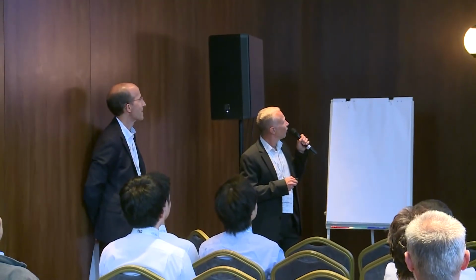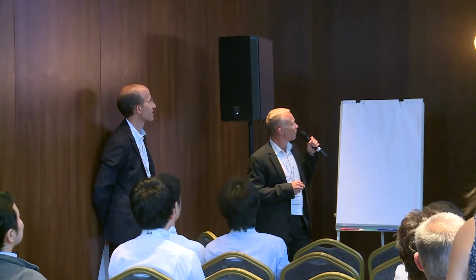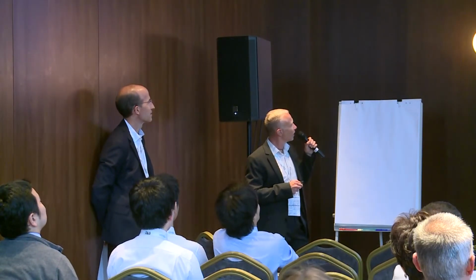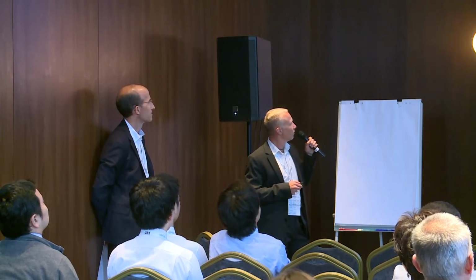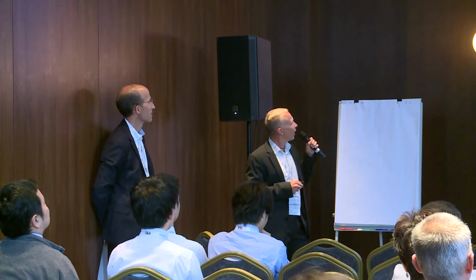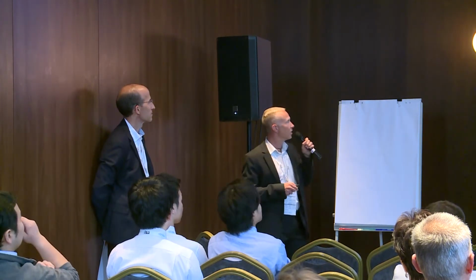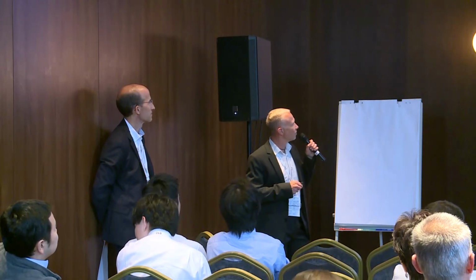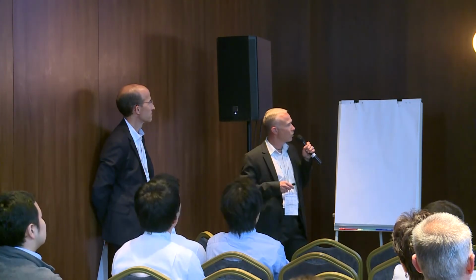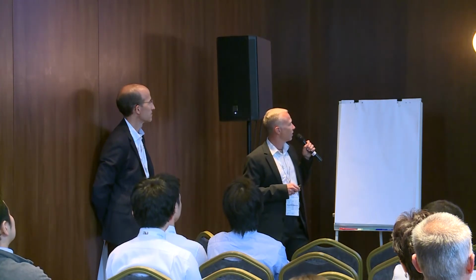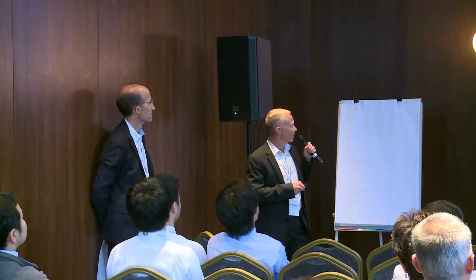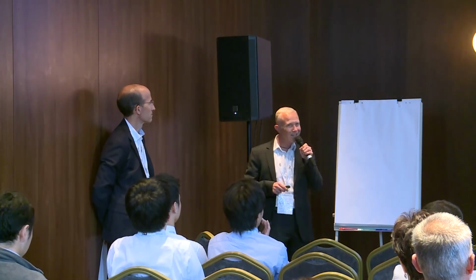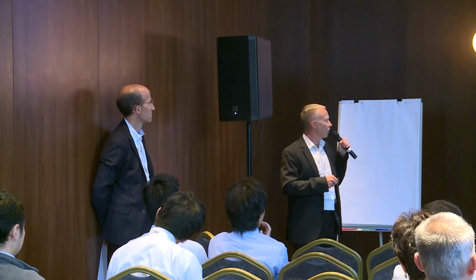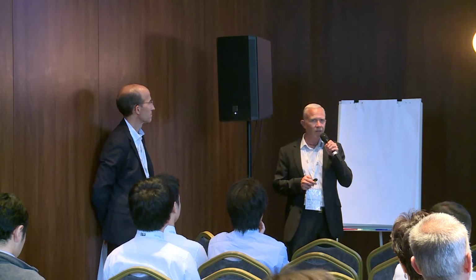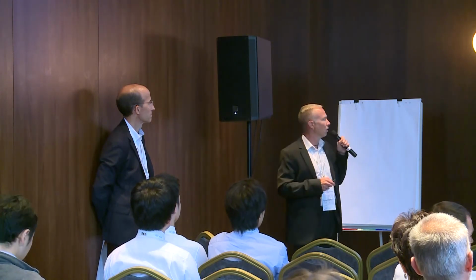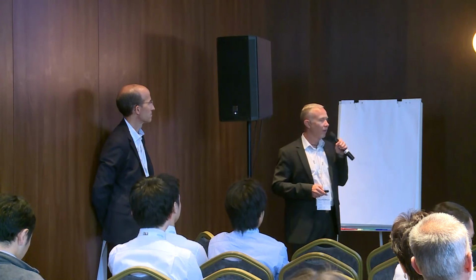Then the conclusion: we have shown that our different techniques can measure the residual stresses, and we also found some kinds of plasticity-induced crack closure, but obviously the residual stresses are responsible for the deceleration of the crack propagation rate, and then the plasticity-induced crack closure is rearranged when the crack is growing through the plastic zone. And very important is also this relaxation process of the residual stresses during a single unloading cycle, and this is very important for the loading history effect and to describe real loadings as you find them for real components.